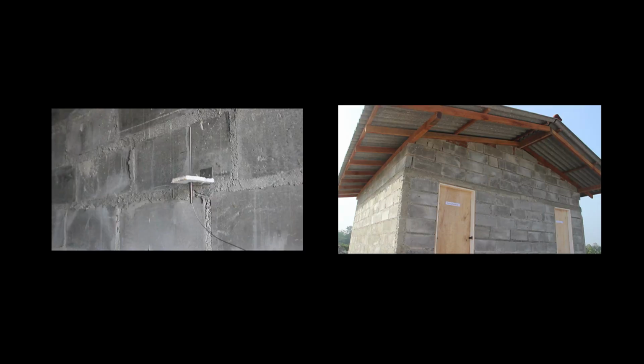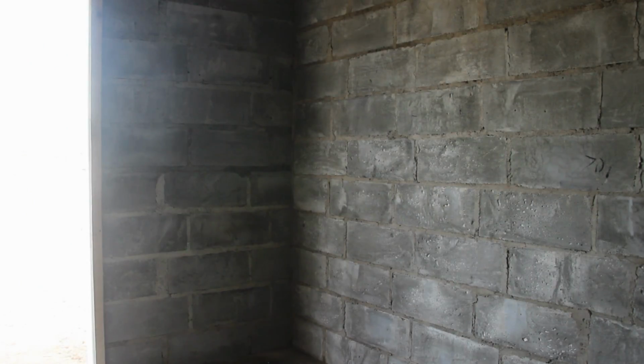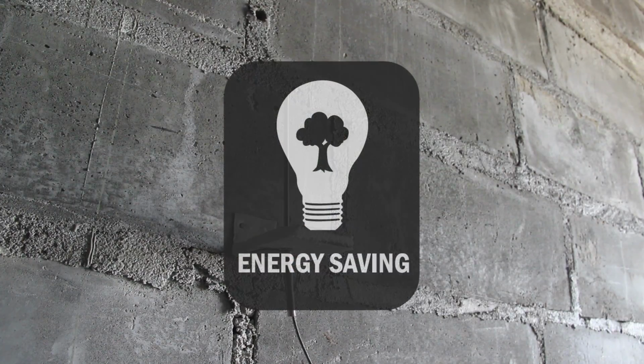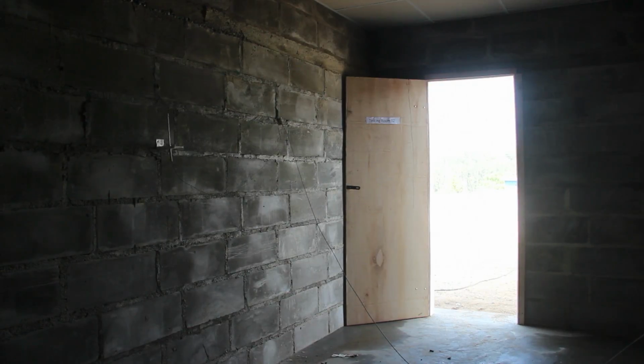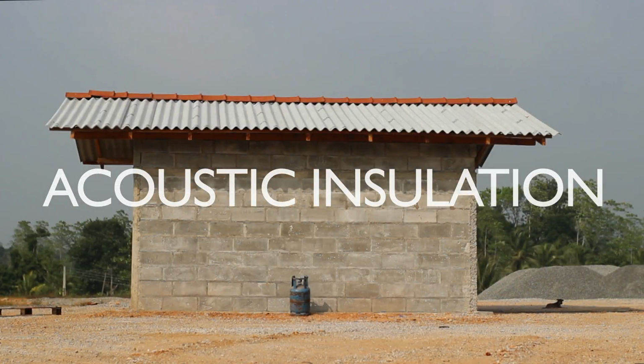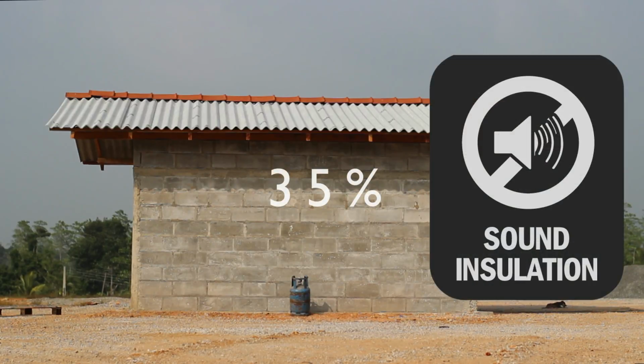The indoor temperature remained between 27 to 30 degrees Celsius, whilst even the outside temperature rose to over 36 degrees Celsius. It is clear from this that the Superlight block substantially reduces peak energy consumption, resulting in financial savings for homeowners, in addition to the comfort of living and a pleasant interior climate. The Superlight block reduces the outside sound by over 35%.